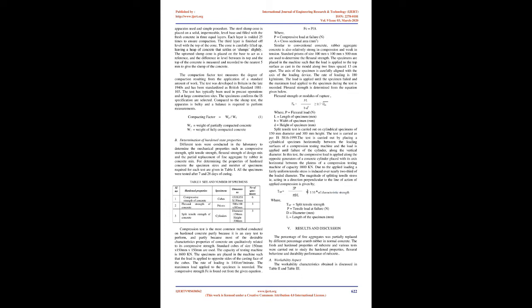According to F. Hernandez Olivares, rubber fiber-filled specimens show larger result dispersions than sets without fiber, and the Gauss distribution is wider in the first case than in the second. It means that fiber-filled concrete is less reliable than the control mix without any fiber, and maximum compressive strength decreases slightly.